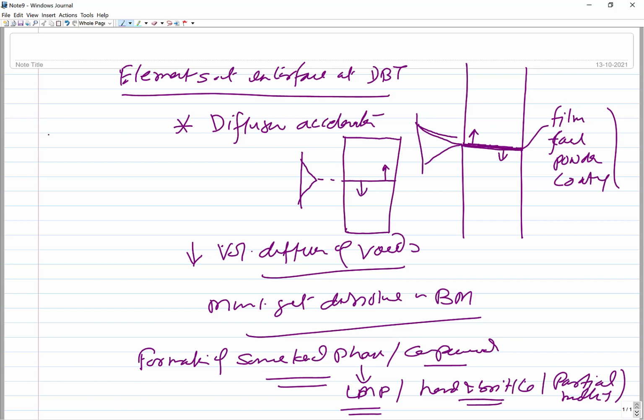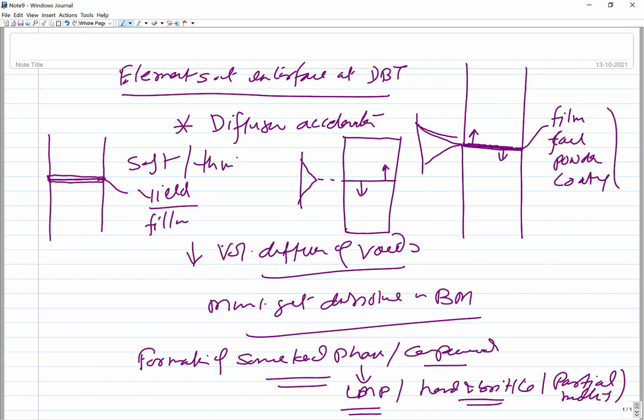Another purpose of using these films and foils is that since these are selected in such a way that these are soft, these are thin, when these are present at the interface under the diffusion bonding temperature and pressure conditions, these will yield, and these will be filling the gaps, voids, to improve the metallic bonding across the interface. So even if the surface is initially rough, when these films and foils are added, under the diffusion bonding temperature and pressure conditions, these will yield and fill up the gaps. Like if the surface is rough, then films may fill up like this. So this kind of filling will improve the metallic bonding between the two components being joined.